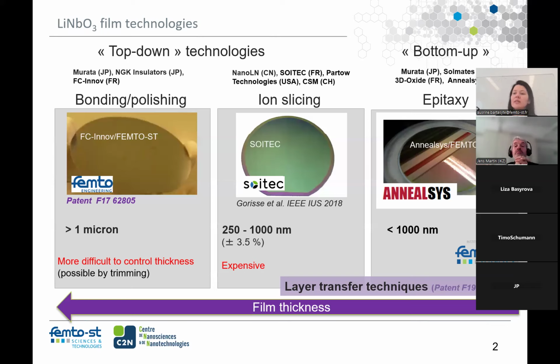The film is still of single crystalline quality, but it has a slight damage effect. It's not that quality when we have polishing. Polishing doesn't damage the crystal structure at all. Implantation will still have some effect on the structure, so it's no longer this perfect single crystal as before. Of course, we did annealing and so on, so mainly the properties are recovered. It's a very high quality film, but it's not exactly the same quality as when you just do polishing. So when we say single crystal, there is some implantation damage, some effect behind.